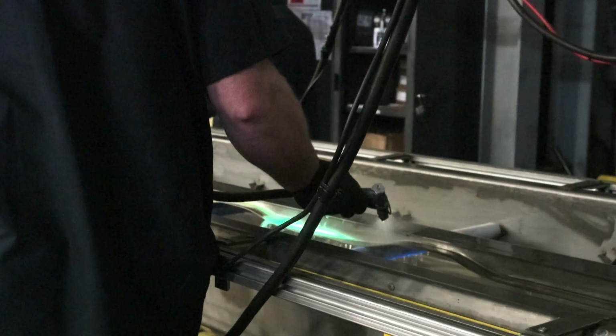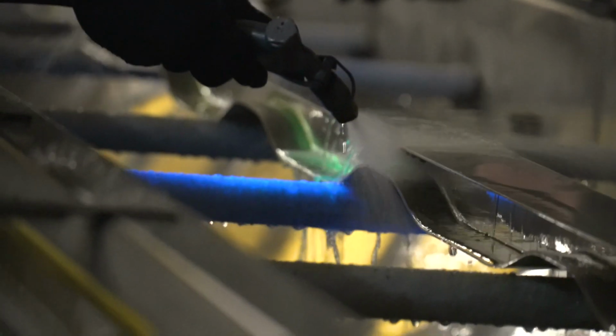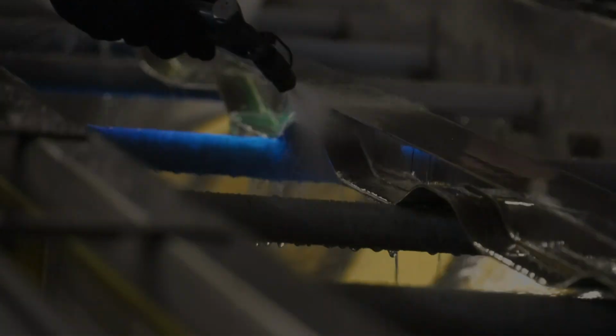We produce about 3 linear miles of seat tracks for the 787 aircraft, which are a titanium weldment that we not only vacuum stress relieve, but we also creep flatten, and we also do an operation, a non-destructive testing of liquid penetrant testing of the welds.